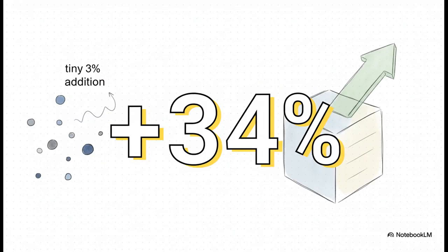But let's not forget about the upside here. The gains in stiffness were really impressive. Just by adding a tiny 3% of this nanofiller, the researchers got up to a 34% increase in the material's flexural modulus. That is a massive performance boost from a really small change to the recipe.